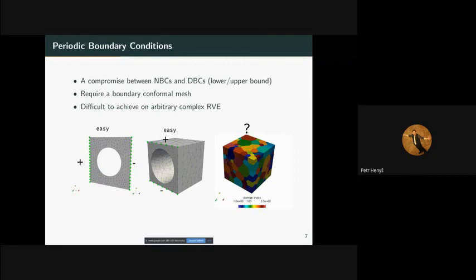But if the geometry is more complex, it doesn't matter if it's a metamaterial or another volume, it's much more difficult to fulfill the periodicity, and it is actually much better to work with a mesh which is not conformal. However, if you want to use a non-conformal mesh for achieving periodicity, you have to modify the finite element model, and that's pretty tricky and needs some parts to be added and controlled. Otherwise, you will not get satisfying results, of course. You can do it. For example, commercial software uses some approaches which, however, are not very effective.